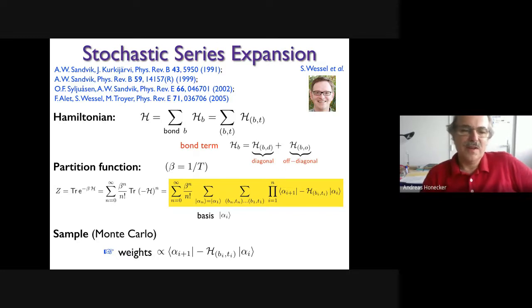With that splitting, you use the high temperature expansion of the partition function, meaning you insert the power series representation for the exponential. And then for the traces of the powers of minus the Hamiltonian, you use matrix elements in a given basis. So you choose a basis, and then you end up with a huge sum of products of terms. That might look nasty, but Monte Carlo is meant exactly for evaluating such huge sums. And you just use these products of matrix elements as your weights.